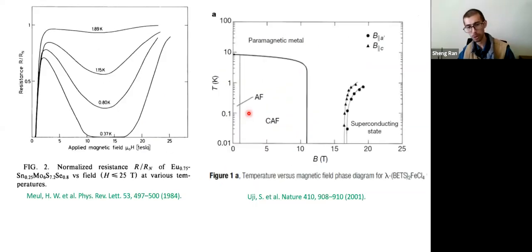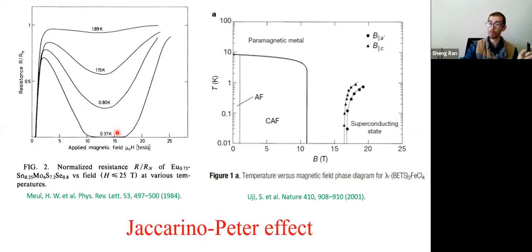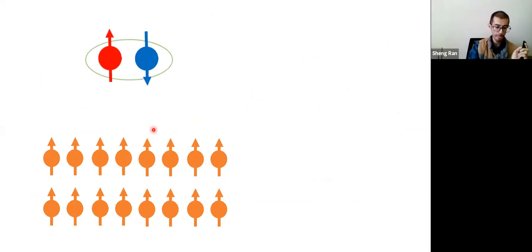Well, this field-induced superconductivity is a surprising phenomenon, but this has been seen. Here I'm showing two compounds, one inorganic compound and one organic compound. In both compounds, you have some superconductivity and it goes to normal state and goes to superconducting state again. But in these two compounds, this has been understood in terms of the so-called Jaccarino-Peter effect. Given the time, I'm gonna skip this. The bottom line is this was understood.